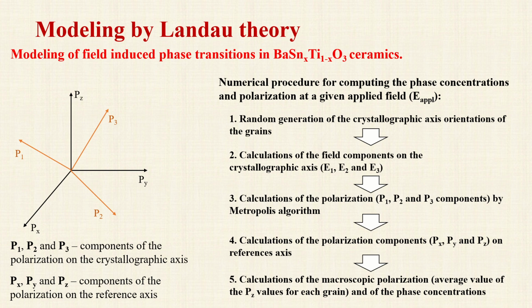After that, the components of the polarization are calculated for each grain on the reference axis, which is in fact the measurement axis. Finally, the macroscopic polarization is computed as an average of the PZ component of each grain. And this procedure is repeated for different values of the external applied electric field.